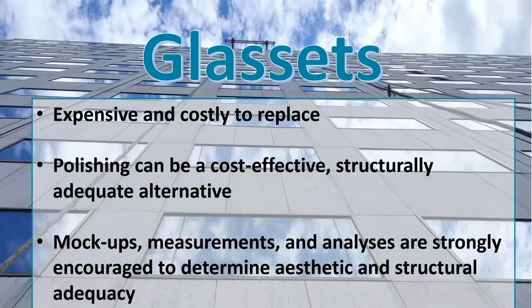And one other thing that I just want to remind everybody that Mark mentioned earlier was that this is highly workmanship sensitive. You have to have the right professionals on the site to come out with a good product, because if you just get somebody that hasn't really done this, they can grind a lens into your window, and then you really do have to replace it, because that's almost not fixable.